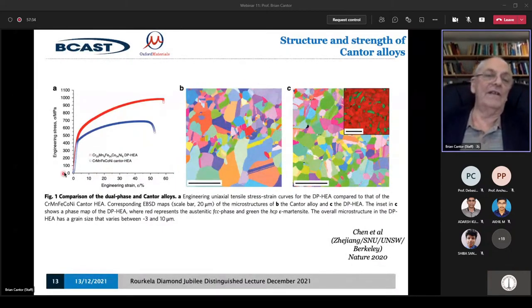So the holy grail for metallurgists and materials scientists has always been, how do you get high strength and high formability? The high formability, of course, also goes with fracture resistance, because what happens is locally the materials begin to change shape, rather than having a crack grow. Cracks can't grow and develop because you get local changes of shape. So formability and fracture resistance are effectively the same thing, linked into the ductility.